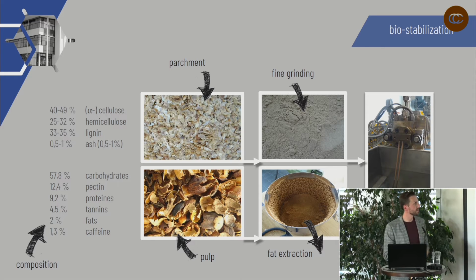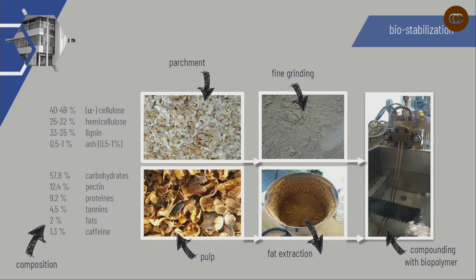What we have done is, for the first time, we took the parchment and the pulp. Here you can see the ingredients and their concentration. For the pulp, for example, it is necessary to make a fat extraction because this can cause problems in the processing. We have to fine grind it, so we create a powder out of that, and we need to dry it because we still have a lot of humidity in these components. We need to take the humidity out because, as you can guess, in the compounding process we have higher temperatures. This would lead to evaporation and finally to some failures.